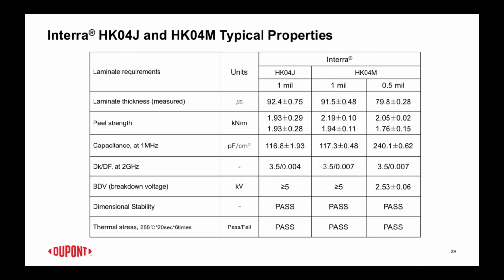So these are the specs of the material, the typical properties. Again, the 1 mil HK04J and M are pretty much drop-in replacements for each other. The only difference is the site of manufacturing, so they have a different UL because of that, but they're basically equivalent. You can see from a thickness standpoint, peel strength, capacitance, dielectric constant, and DF, they all pretty much overlap each other. They have excellent breakdown voltage because these are polyimide based. They're very strong materials, both electrically and mechanically.